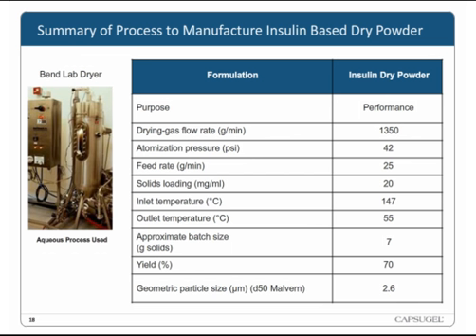So here I'll just highlight the drying gas flow rate, atomization, feed rate, the solids loading, which is about 2 weight%, and then the inlet temperature, which seems high for a biotherapeutic, but because of the evaporative cooling that happens right away, the product really only sees the outlet temperature, which is around 55 degrees C. As discussed in the paper, the 55 degree process conditions were selected because we had measured the glass transition temperature of the dextran as much, much higher than that, even at the relative saturation of the dryer, which I think was around 4 to 6% relative humidity.